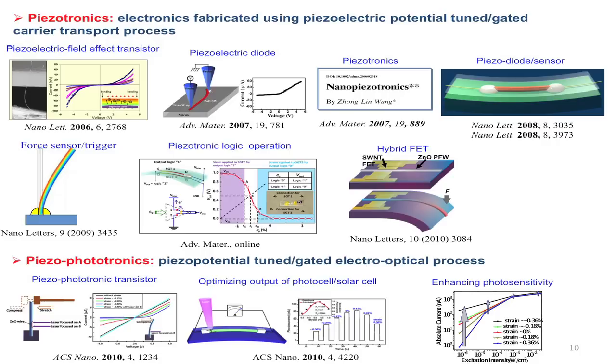We can artificially change the barrier height. Because if this barrier height is too high, no electron-hole pairs can be separated. That doesn't work. If it's too low, the electron-hole pairs separate but they can recombine. So what is the best height? The best height is that we can continuously raise the barrier height by piezoelectric effect until you get the very best photo sensitivity. Utilizing this, we have fabricated UV sensors at very dim light that enhance the sensitivity by 300 times. Just one device. Just apply strain. You produce piezoelectric effect that raises the sensitivity 300 times.